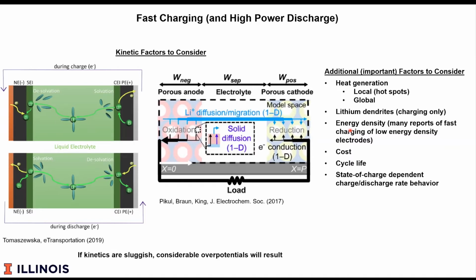There are reports in the literature of being able to reduce lithium dendrite by loading the anode with gold nanoparticles. That might be possible if the gold is present in very low volume fractions, but probably not in practical, realistic volume fractions. Another factor is cycle life. As we know, we want batteries to be able to charge and discharge hundreds or thousands of times. And so while these issues due to heating or dendrite may not show up in the first 10 or 20 or even a few hundred cycles, they may show up over time. And so what one finds is that when batteries are fast charged or high power discharged, they may work fine for a little while, but then over time, the capacity will fade.